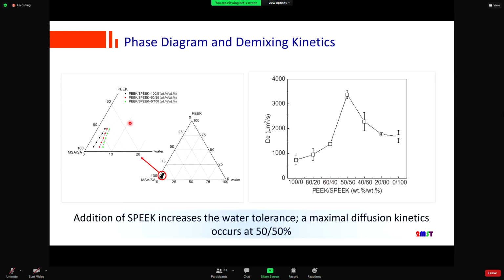Again, the thermodynamic measurement indicates that when you add SPEEK into the system, it becomes more water compatible, but still not tolerable to a large amount of water. Interestingly, we have seen that the nominal diffusion coefficient of the polymer system in demixing reaches a peak at 50-50%, which is probably because of the percolation of the two polymers during demixing.